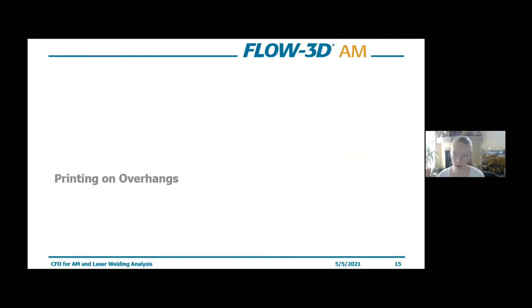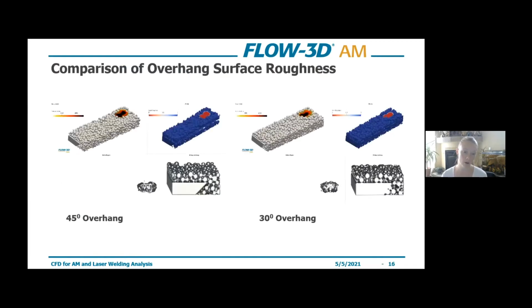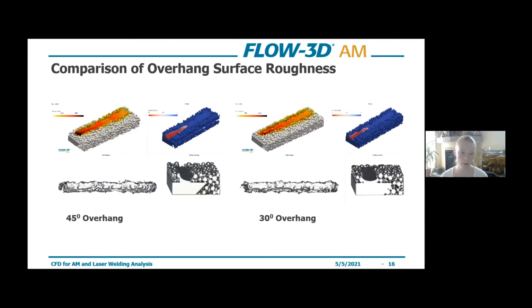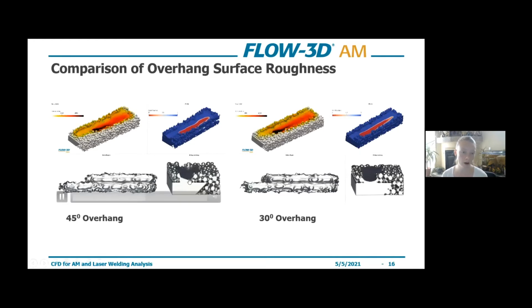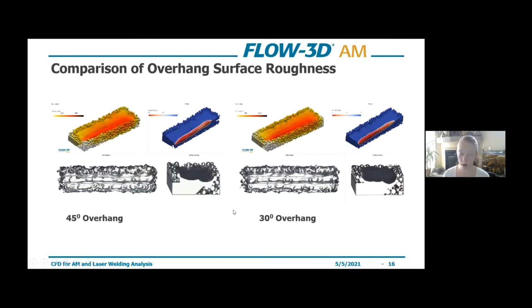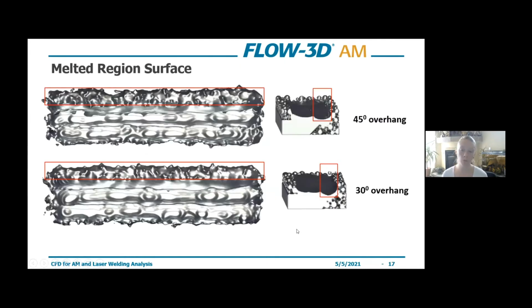Now, printing on overhangs is another area of interest that's been coming up more recently for us. I'm sure many people are looking into how you can print more detailed geometries, how you can go from one media to the next without leading to different kinds of defects that come with that territory. In this example, this is a sample case of printing on an overhang where the first two tracks are on the solid base material, and then the third track is where you're going onto the overhang where it's primarily powder. We're looking at the difference between a 45-degree overhang and a 30-degree overhang. And what we can do in Flow3D AM is extract the melted region, and then we can look at the downskin surface roughness to see what kind of fusion conditions we're getting, what kind of surface roughness we're getting.